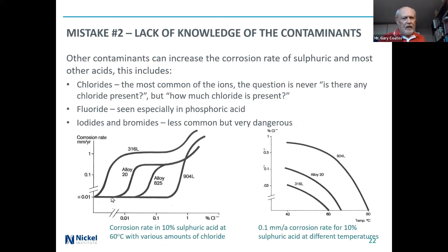In other alloys, they could tolerate more and more amounts of chloride, and here 904L with the highest molybdenum content tolerated the highest amount of chloride, but even with a sufficient amount of chloride, it also became active. And this is active corrosion, so it isn't pitting, it's high corrosion rates there. So you have to be very careful with chloride, and the curve on the right is just another way of presenting the same information based on the temperature, where the one on the left was 60 degrees C, this puts the temperature as one of the variables.